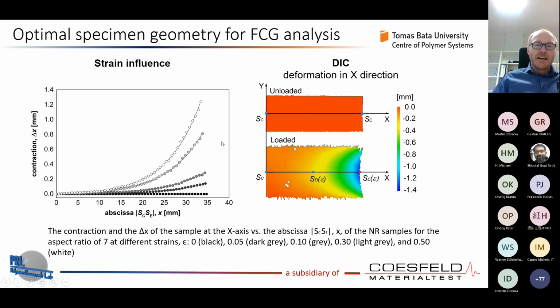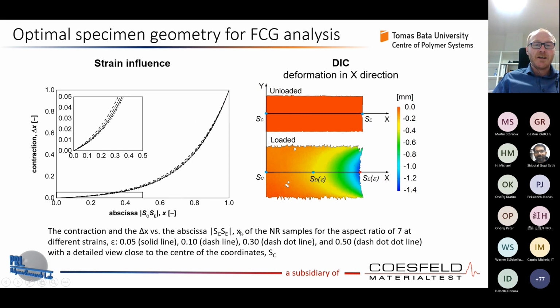So what you can see, as a first step, is the strain influence: whether there is an influence of strain on the deformation in this direction. If you see such a diagram for different strains, you will say, yes, maybe there is an influence. However, then I will show you something. I will normalize this diagram now. And what I get for all strains from 0.05 up to 0.5, 50%, is no difference.